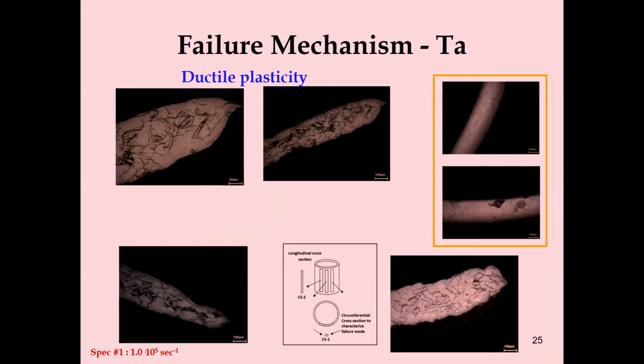We did the same for tantalum. They're not as interesting. We see again all this extensive plastic deformation, twinning, etc. But one interesting thing is, as we look at the edges of these fragments, we could see this kind of pinching, which is very characteristic when you look at quasi-static testing of tantalum and even with Hopkinson experiments. But we were expecting, as we got to very high strain rates, to see something a bit more brittle, but it's surprisingly very nice how we're looking at this kind of pinching behavior, just as we see at the lower regime. And we're looking forward to the newer experiments we're going to see in the next few weeks and months.